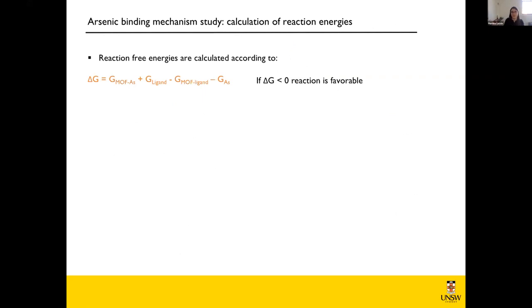And this is done like you would expect, by taking the free energy of the products, the MOF bound to the arsenic and the ligand that was displaced, and subtracting the energy of the reactants. And just like you would expect, if you see a reaction free energy below 0, that means the reaction is favorable, and the more negative it is, the better.